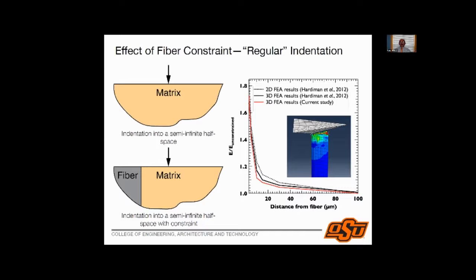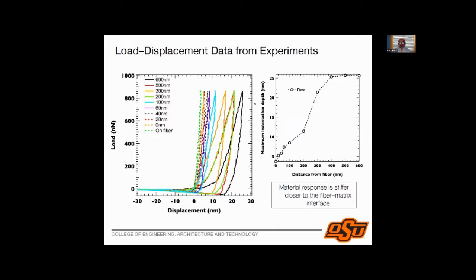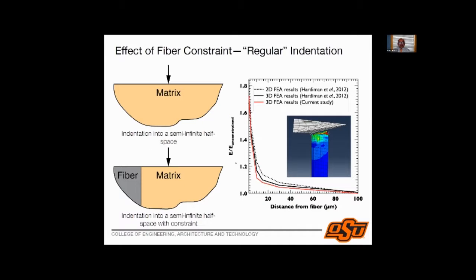In a regular nanoindentation experiment, I take the load displacement curve and I analyze it using analytical equations. Basically I look at the unloading curve, and from the unloading curve, I can get what the modulus is. But I need analytical equations. So we have the elastic solution of an indentation on a semi-infinite half space. We've always had this. This is how I analyze my regular indentation data.